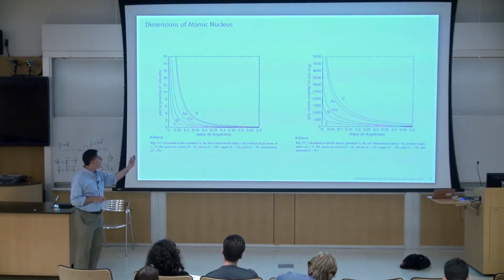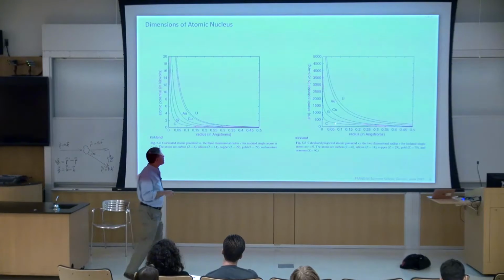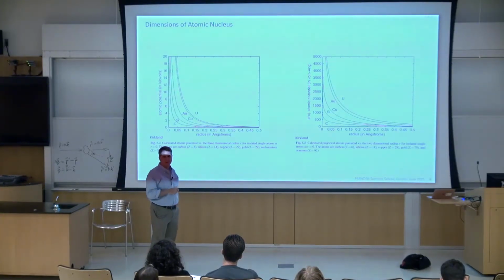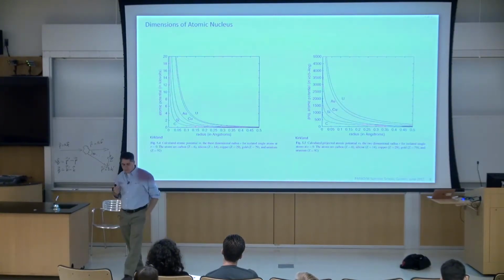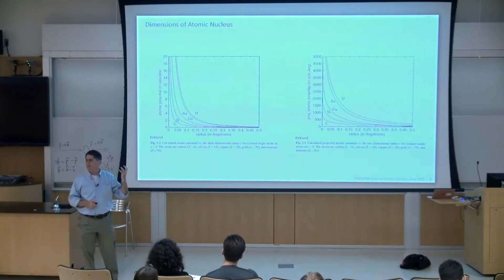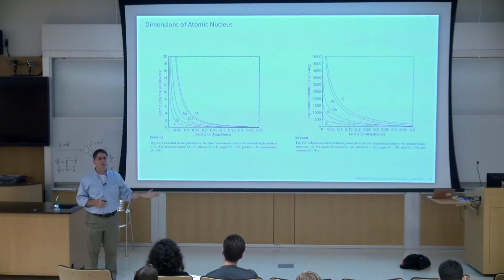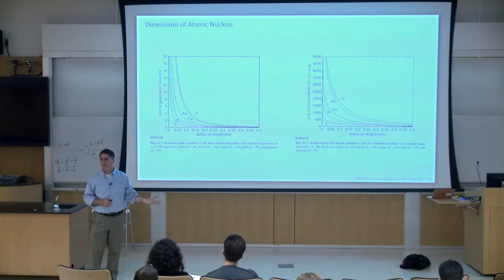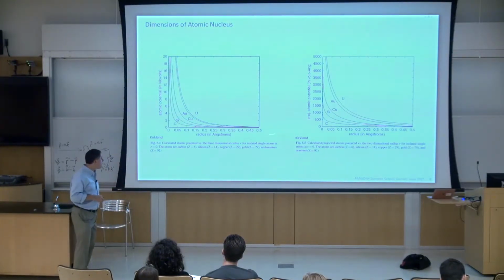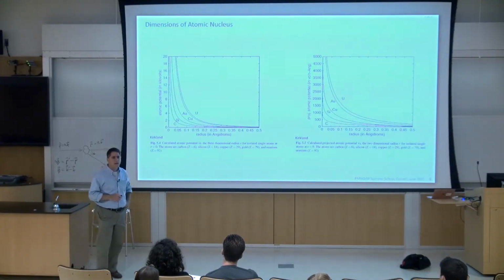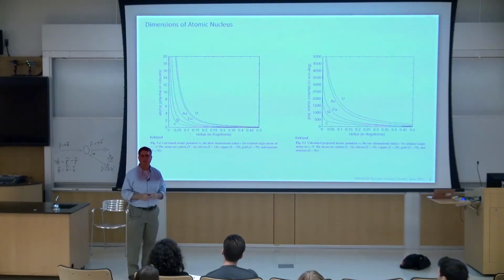So the shape of the potential, most of it is stuck within 0.1 angstroms of the nucleus. The potential of an atom is mostly the nuclear potential plus the electrons, but most of the electrons are core electrons, which are close to the nucleus. So the whole thing looks basically almost like a delta function. And that means when you Fourier transform it, what's its angular distribution?